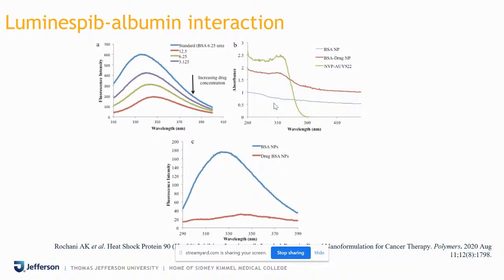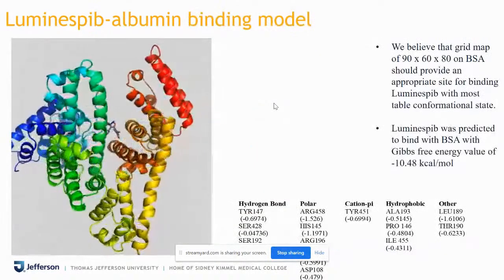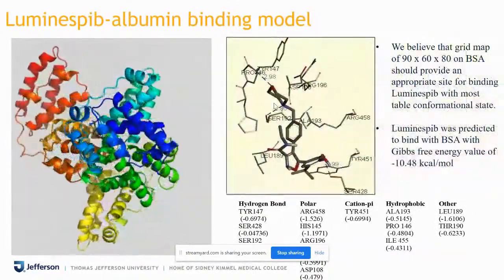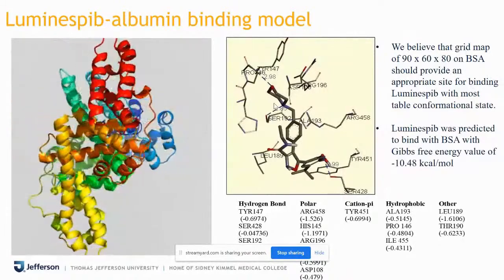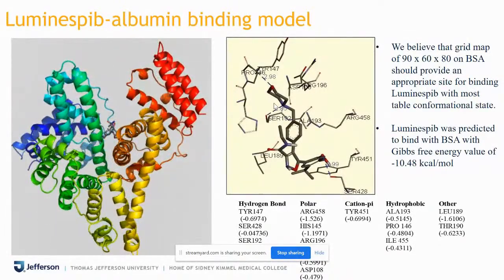Now, since it was interacting with the albumin, it posed a question: where would it go and bind in this protein? So we performed a classical blind docking study, where we thought that the drug would go and bind to any place in the albumin structure. We created a grid box of 90 by 60 by 80, which covered the entire structure of the protein. We asked the software AutoDock to dock this molecule and give us the Gibbs free binding energy for various structures that can come out. We found that this conformation, shown in the model, is the most stable one, with a Gibbs free energy of minus 10.48 kilocalorie per mole.